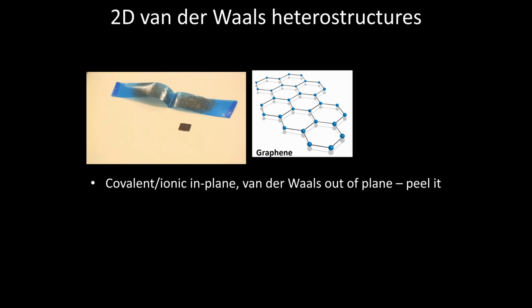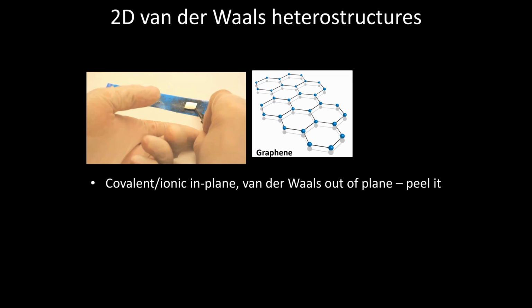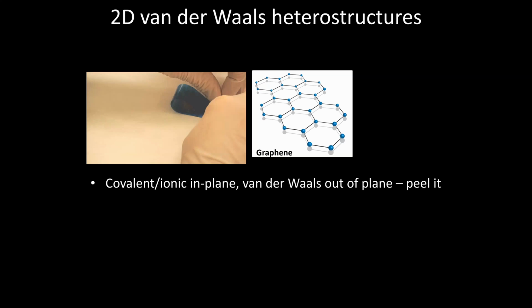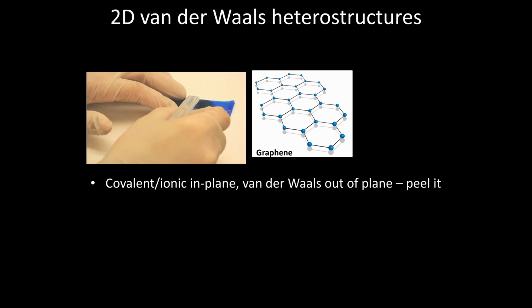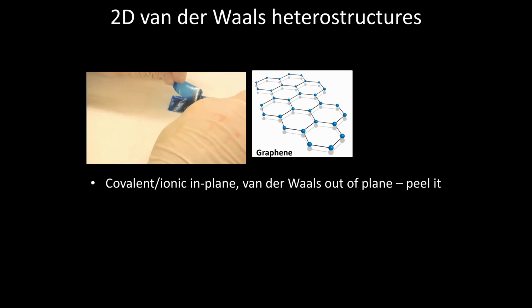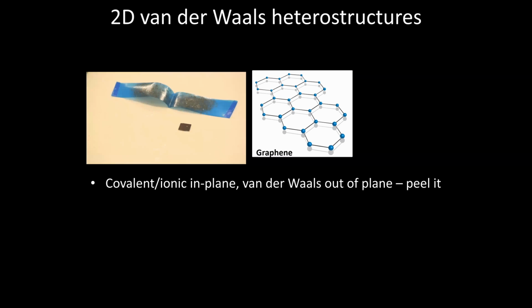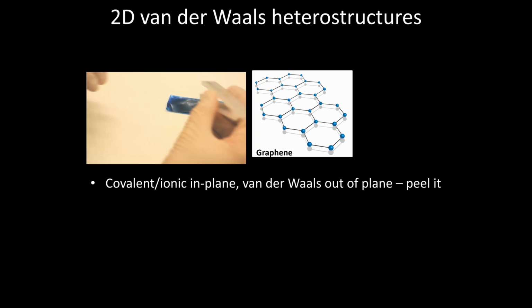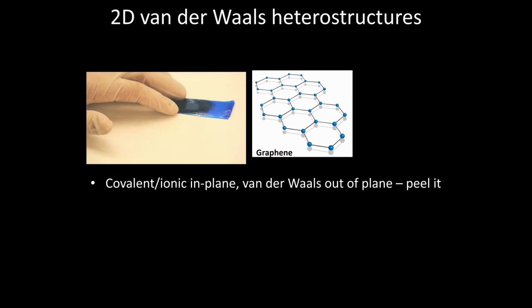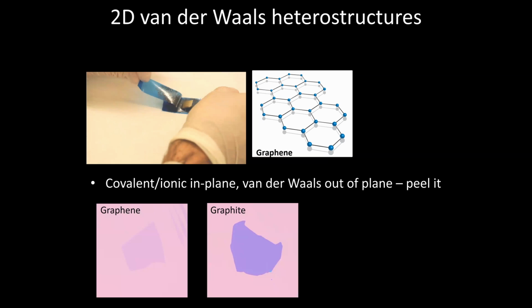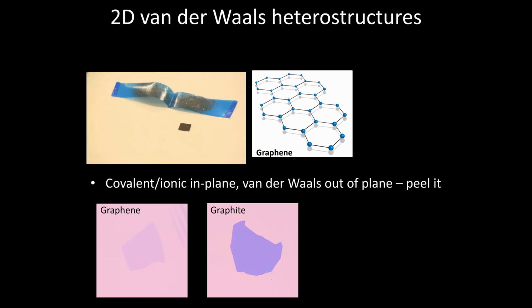We study two-dimensional layered materials. It remains to this day, again, as David sadly reminded me, nearly 20 years after the discovery of graphene, we still basically make it the same way because it's the best way to make it, which is to start from clean bulk graphite and essentially peel it with Scotch tape. You can do it in more sophisticated ways, but it makes absolutely no difference. You get sort of the same result at the end, which is reasonably large sized, tens of microns or a couple hundred micron size flakes of graphene.